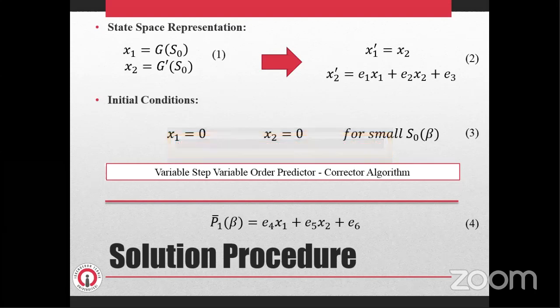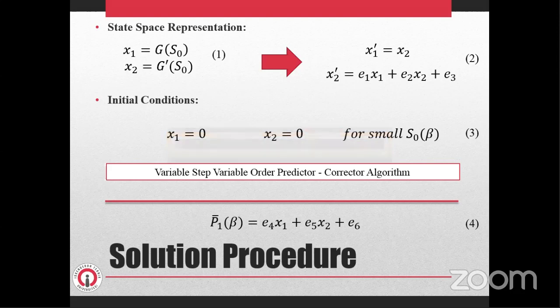The state variables are defined as equation 1. After that, the first equation is written as equation 2, where quotation marks show the differential with respect to the mean shell thickness, and coefficients E_i are functions of mean shell thickness and other time independent coefficients. The solution of this stiff problem is obtained by using a variable step variable order predictor corrector algorithm.